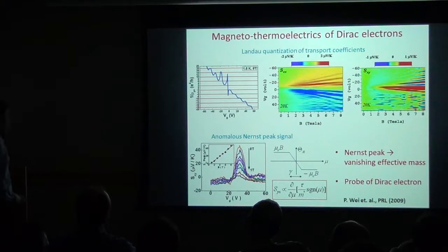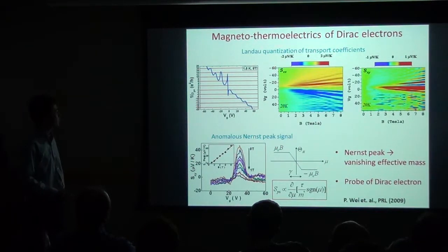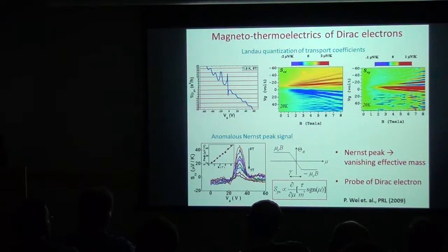To further study how novel the thermoelectric transport is in this Dirac electron system, we quantize the system into a quantum Hall regime by cooling down to a low temperature of 1.6 K and applying an 8 Tesla magnetic field. In that case, the electrons form Landau levels and edge states. And in graphene, a characteristic quantum Hall state is the half-integer quantum Hall plateau, which indicates Dirac electrons.